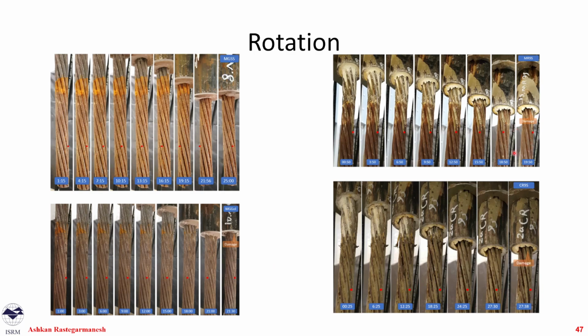And for resin, again, we see the same thing, but this is a bolt cable. So in these two bolt cables, we actually see less rotation during the test at the entry point. And when it finishes, it almost went back to the normal position, which we can basically postulate is because the bolt is damaging, scraping the inside of this annulus compared to these plain cables. It makes a way for itself to not store the rotation and the cable to eventually move back to where it was. But in plain cables, the strands are basically traveling through the path of least resistance.